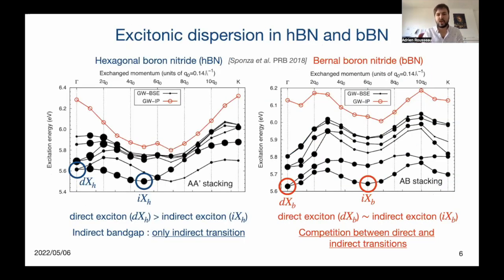The excitonic dispersion in hexagonal boron nitride and Bernal boron nitride has been calculated using ab initio calculation by Sponza et al. in 2018. The excitonic dispersion of both hexagonal boron nitride and Bernal boron nitride sit at almost the same energy range. Nonetheless, the excitonic dispersion in Bernal boron nitride is at slightly higher energy and is flatter than the one of hexagonal boron nitride.